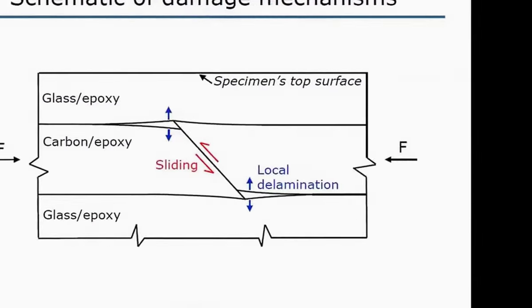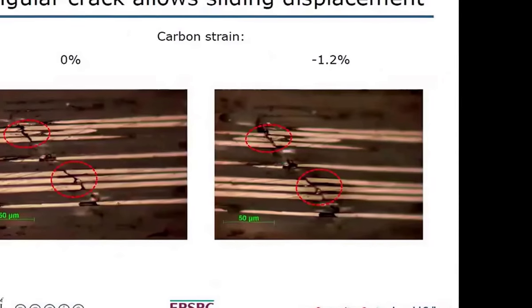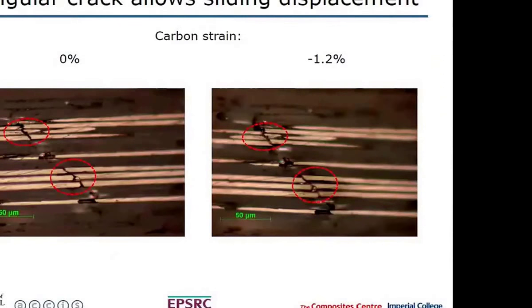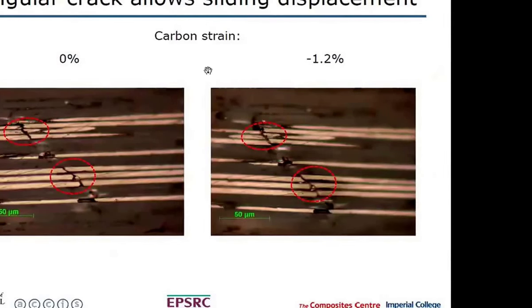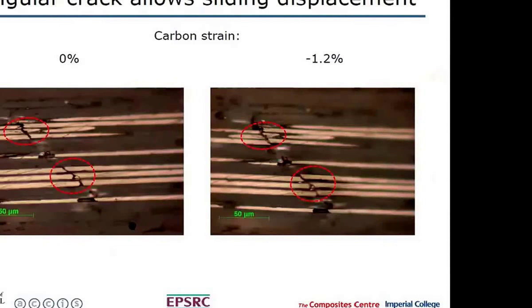So looking back to these ones here, the ones under tension. The tiger stripe. Yeah. The multiple fragmentation from shear lag that we get, do they congregate within the adjacent carbon ply, or is it well distributed throughout the carbon ply in the high spectrum? So it's pretty much distributed throughout the whole thing.